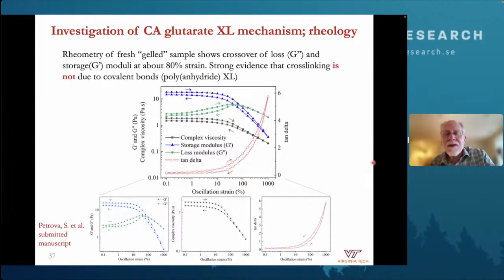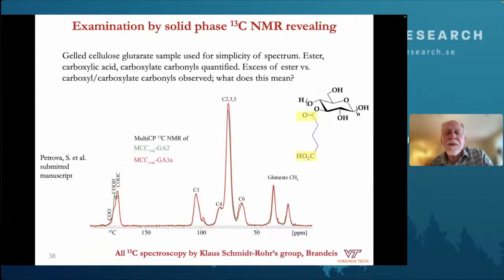But Stella did rheological studies, and long story short, what she saw was that with strain, you could break the crosslinks. That means they're not covalent, which means polyanhydride is probably not the mechanism. Covalent bonds are not the mechanism of gelation here.